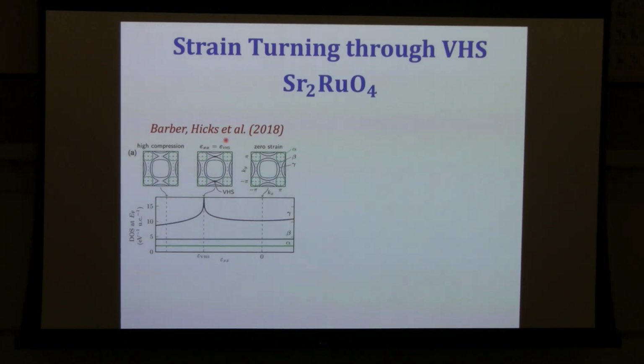Cliff Hicks, who's a Stanford alumnus, did this beautiful experiment where it's a tetragonal system, meaning that the crystal has a square symmetry. And by applying strain, you can modify the electronic dispersion of the different bands in this system. At zero strain, there's a particular band called the gamma band, which is naturally very close to the boundary of the Brillouin zone. So it doesn't take a lot of compression or tension to bring the Fermi surface to the zone edge, where it meets its Bragg reflection and undergoes this Van Hove singularity.